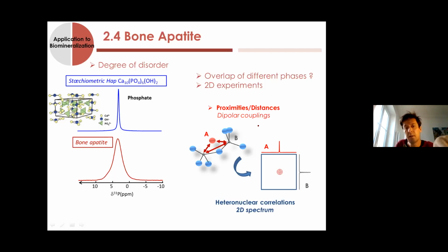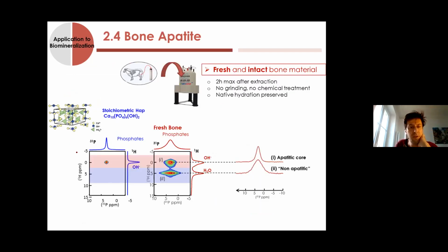If you look now at the proximities between, for instance, the phosphorus and the proton, you can get another fingerprint, this time in 2D - the correlation between phosphorus and proton in the case of stoichiometric apatite. You see here a correlation resonance showing that your phosphate in the structure is close, about 4-5 angstroms, to the proton in the hydroxyl group.